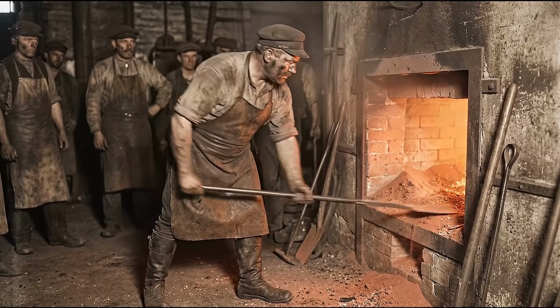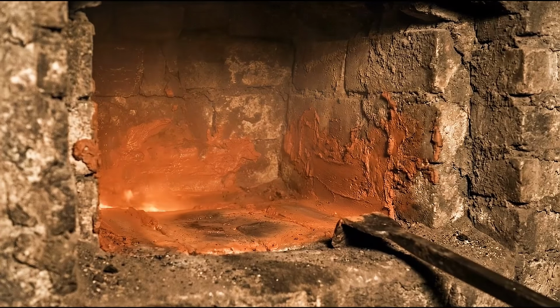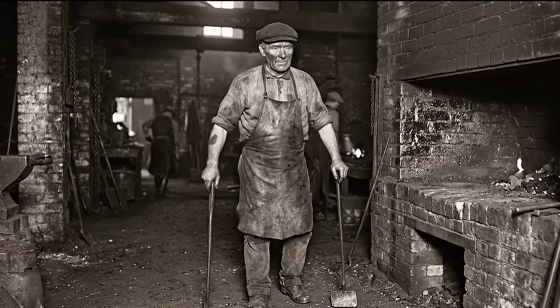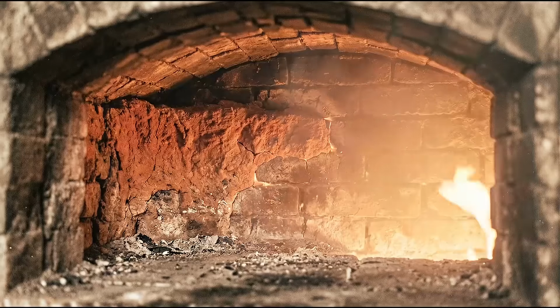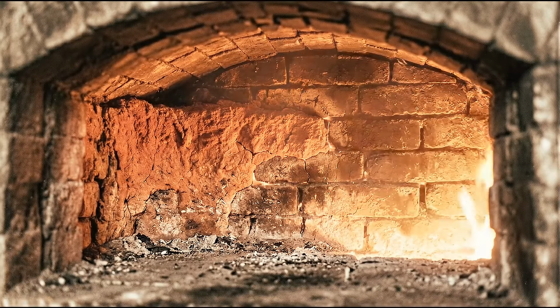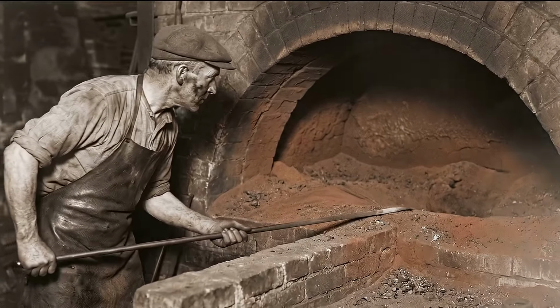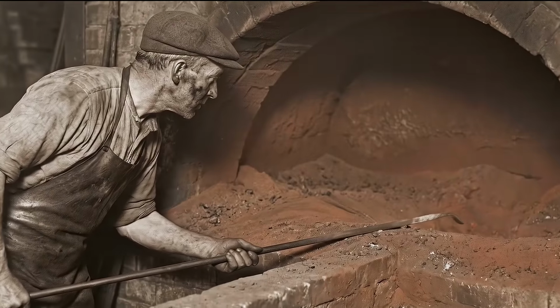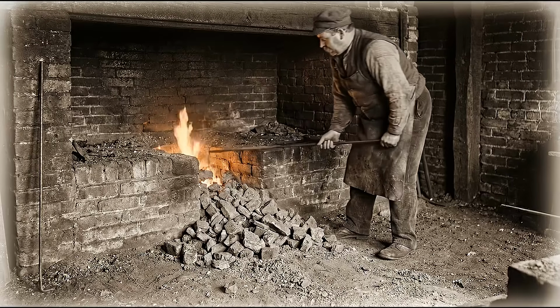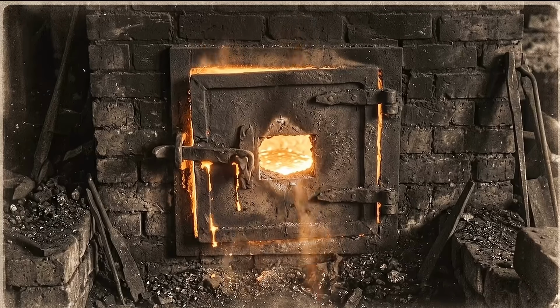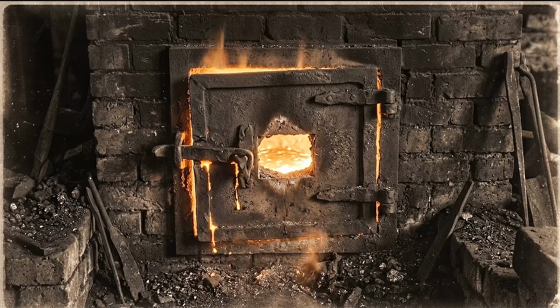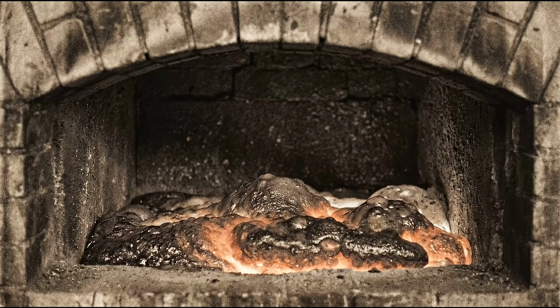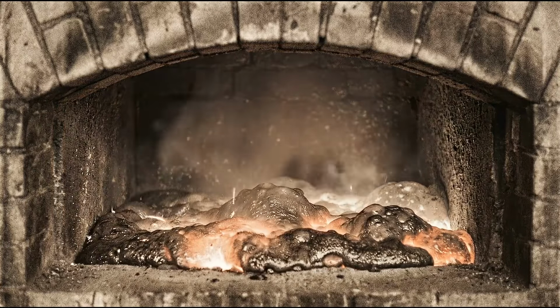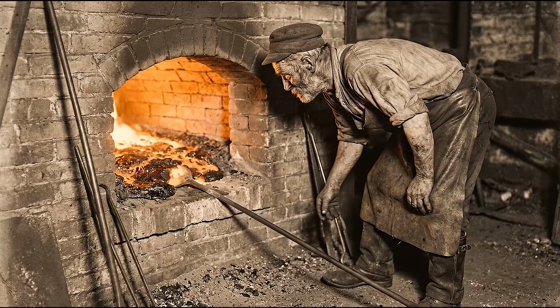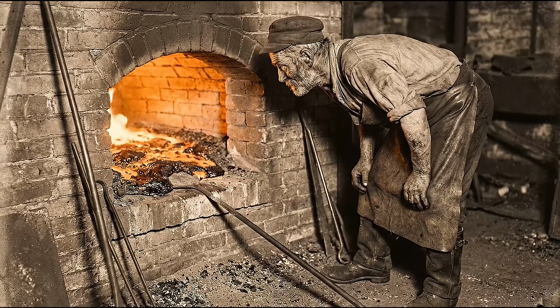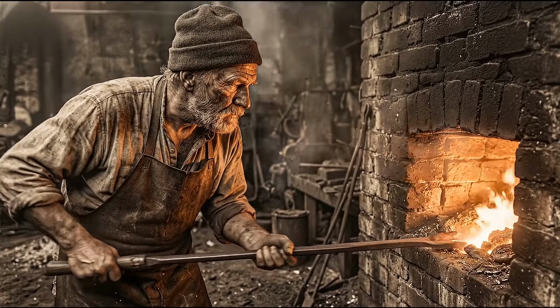Before loading any iron, the puddler prepared the furnace by coating the hearth and walls with hematite, a reddish iron oxide. This step was called fettling, and it served two purposes. The coating protected the furnace lining from the extreme temperatures, and the iron oxide itself supplied extra oxygen that would help burn off impurities during the refining process. Then the puddler loaded 300 to 400 pounds of broken pig iron into the hearth and sealed the furnace door. As the temperature climbed, the iron melted into a shimmering pool. Carbon began to burn off. Carbon dioxide bubbled up through the liquid metal and made the layer of slag floating on top puff and swell. Experienced puddlers watched that slag carefully. The way it rose and shifted told them exactly how the refining was progressing.